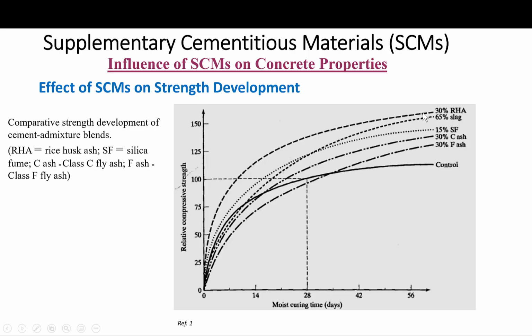The silica fume and the rice husk ash both had higher early strength than the control mix, as mentioned on the previous slide, due to their high reactivity. Overall, long-term strength is higher for all SCMs at all replacement levels.